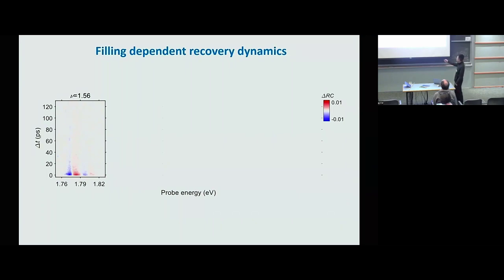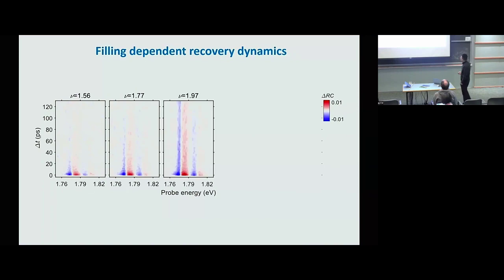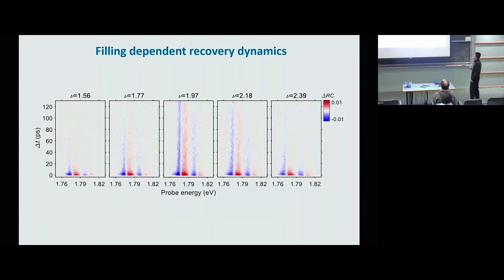Here, this plot shows a specific filling at 1.56. We can see that the signal disappears after about 45 to 50 picoseconds. Then we can change the filling and do the same measurement. So this is 1.77, and 1.97, and 2.18, and 2.39. It's obvious that the dynamics change dramatically over this range. In particular, we see that the relaxation becomes very slow near 2. To be more specific, it's in the range between 1.7 and 2.4.